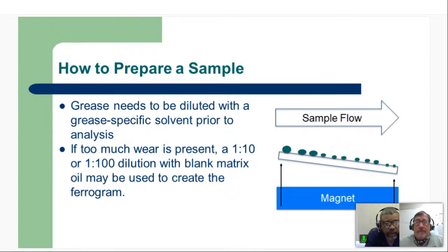That's why your instrument's pretty good in terms of extracting the proper amount of grease from the closest to the wearing surfaces, so that when it does come out, we can weigh it or make sure you have the right weight and so forth. And then when you compare what's going on, then you can evaluate properly what you see. Because there's nothing worse than making false claims. Once you make a false indicator of what's going on, it blows up your, how do I call it, your credibility. Yeah, kind of. It can be that, or sometimes it even works to undermine the technology, right? People say, "Hey, I tried that grease analysis before. It didn't work. They didn't find this, or they said something was there and it wasn't." Yep, it can be hard to recover from.